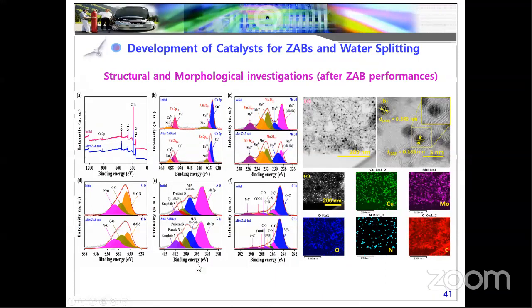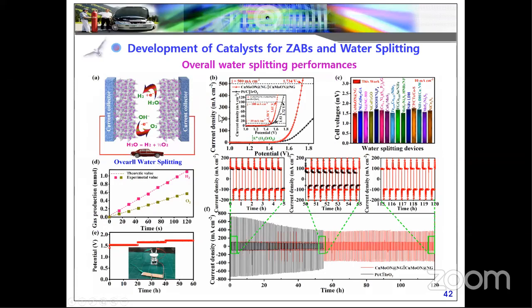These morphological investigations further confirmed our material after the zinc air battery performances. The peaks are almost retained, even the nitrogen is almost retained, and in the morphology you can see the Co shell prevented the active catalyst from degradation. From these studies, the Co shell is one of the active media to prevent degradation, and the materials are uniformly distributed because the element distribution is uniform. From these studies, we conclude our material is more stable toward the zinc air battery and overall water splitting.